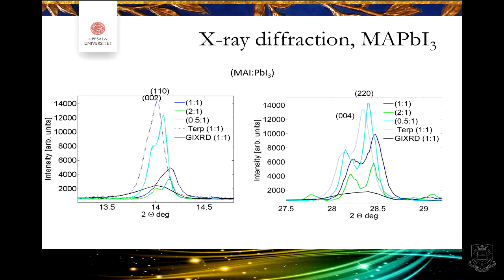So here I'm still working with MAPI, this simple and most classical version, and here I have measured with different XRD machines. So this black line here is grazing incident XRD, and in our lab, our grazing incident XRD has not that high resolution, as you can see. If I would measure this material with that machine, I would just see that, okay, it's cubic, more or less. It's just one peak. But if you have other types of characterization techniques or diffraction measurements.